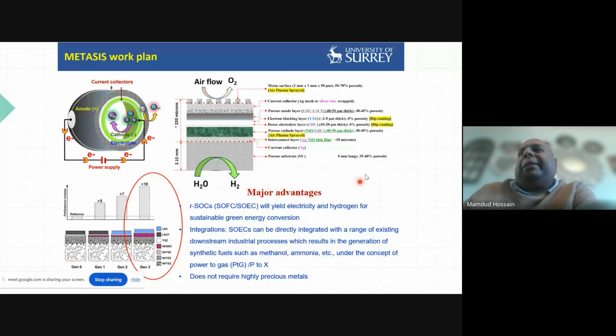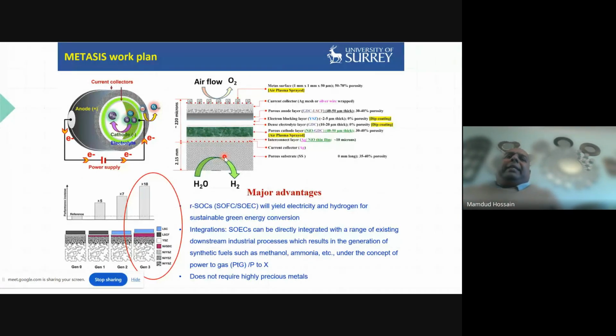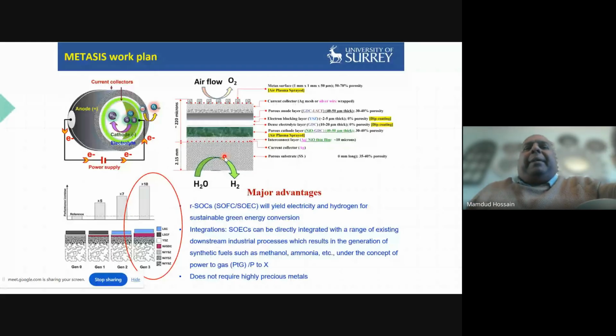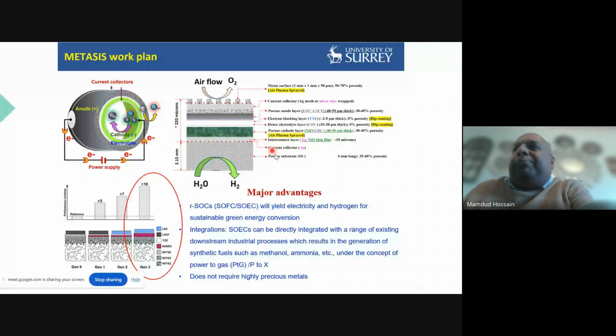Now the structure we invented needs a support material, so we put a support first. The support material is made of porous stainless steel to give you strength, because it's working at high temperature and sometimes high pressure also. On top of the support material, we put a current collector, which is Ag. Then we put an interconnector layer to make the current flow: Ag nickel oxide thin film, 10 micron.